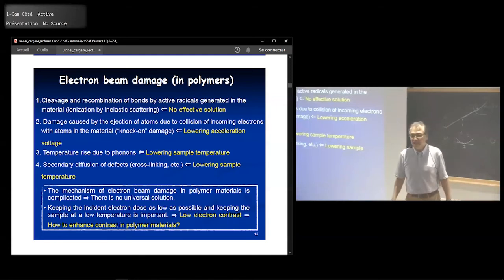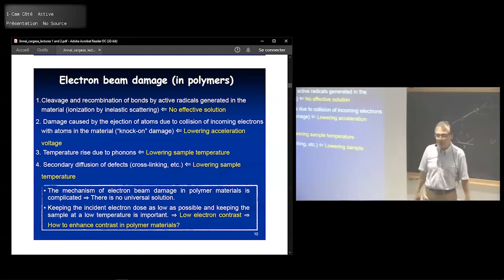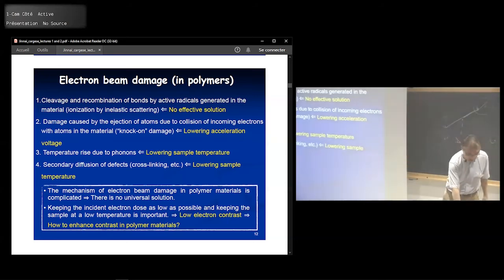What about the electrical charge accumulation? It's a problem too, but it's not a damage. If you accumulate the static, the sample moves around. Instead of damaging the sample, because of static, the sample just moves around. So in order to prevent that, you coat a thin layer of carbon, for example, on top of the sample. Then you prevent that kind of thing.